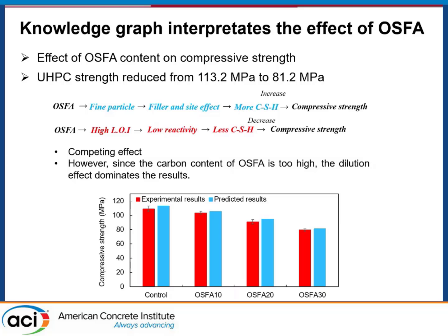But it also has some competing effect, in that the OSFA has finer particle size than the cement. And it has the filler effect, which could promote the cement hydration and increase the compressive strength. But for the OSFA here, as it has very high carbon content, the dilution effects dominate the results.